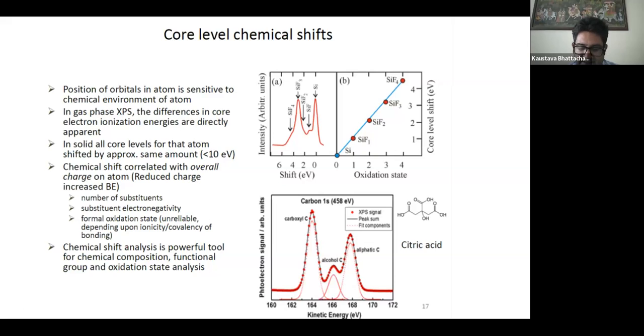So first of all, XPS doesn't see the entity as a compound. XPS always sees the entity as a particular element. So wherever, we will be getting the peaks for Si and fluorine together. And as the core level shift changes, as the charge or the oxidation state of the silicon alters, the drawing out of the electron from that silicon will be different. So its binding energy will shift, and we can say exactly what the oxidation state is, or relate the exact value of the binding energy of the silicon to the charge that is being bound.